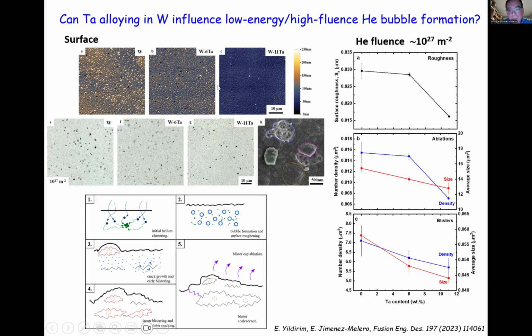You see quite some roughness, and then you see all those black dots, which are blisters and protrusions, right? It's ablations as well, because some of the material at the end ends up being released from the surface. That surface roughness depends on how much tantalum we put in, so that's good news. And that behavior seems to correlate with the number of blisters, but especially the ablations.